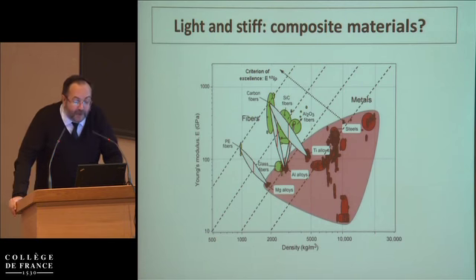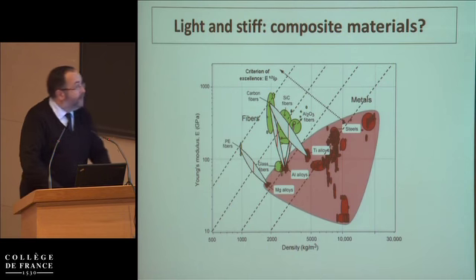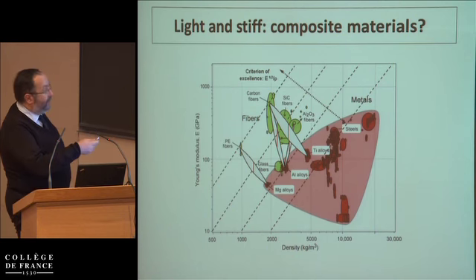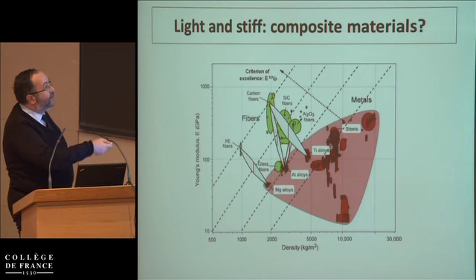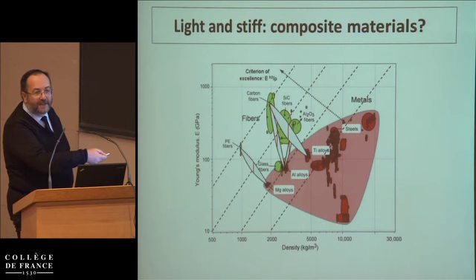Here this mixture would be, for instance, between titanium alloy and carbon fibers. And these two materials here, titanium alloy, which is represented in this place here, that's a diagram with the Young modulus and the density. The carbon fibers are here, and the properties of the mixture between titanium alloy and carbon fibers will lie somewhere here. These boundaries are given by micromechanics models, and this maximum here is given by the processability, which is how much carbon fibers can you introduce into a titanium alloy.